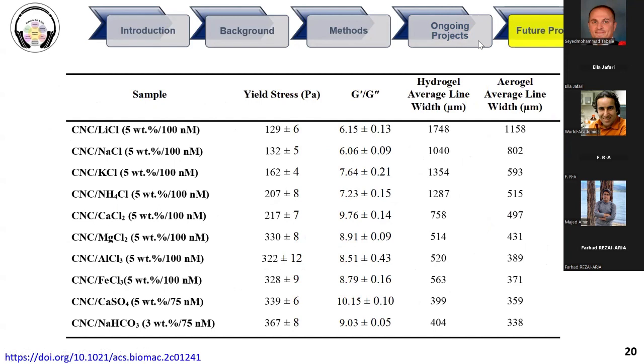We can find how yield stress and the ratio of G prime over G double prime can tell us the printing quality. Here in the last row, we can see the hydrogel and aerogel average line width. The needle that I used for printing these samples was 250 micron. Whenever our number is closer to 250, it means that we printed a high quality sample, because the width of the line is almost the same as the needle diameter.